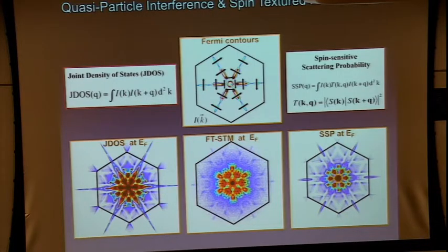This was known, and this we assumed. And essentially, from that, we can then just simply put in here a matrix element having to do with the spin texture of the Fermi surface. Okay, so the spin texture is going to suppress the scattering considerably, and this is what happens. This is the joint density of states from the auto-convolution of ARPES. This is including this matrix element.